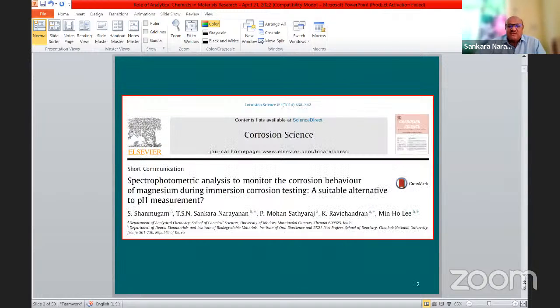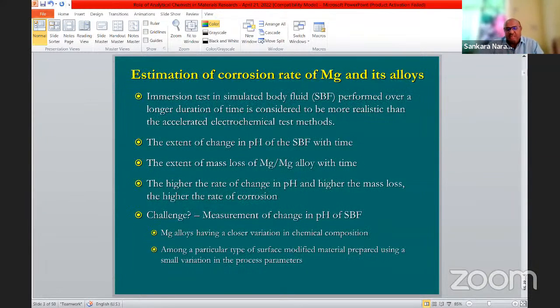So let me repeat it. We have developed a spectrophotometric method to monitor the corrosion behavior of magnesium. Generally, people follow electrochemical measurements, but it is generally believed that an immersion test performed over a longer period of time is more realistic than the accelerated electrochemical test. So one thing we want to do is measure the change in pH of the simulated body fluid.